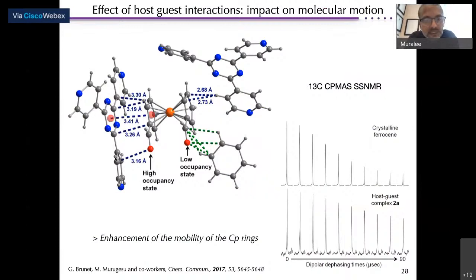When you look at the X-ray structure carefully, at how the ferrocene or ferrocene aldehyde is located, you can see these host-guest interactions as shown here, and some of them are high occupancy sites and some of them are low occupancy sites. You can see clearly the interaction between the framework and the guest molecules. Some of this pi stacking is happening here.